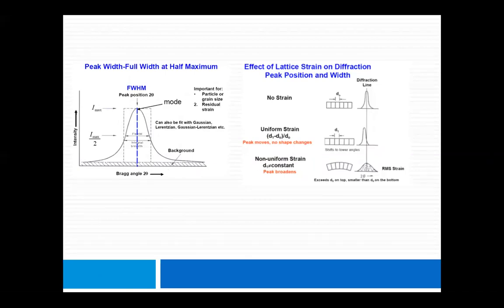So even if you have synthesized particles of the same size by different routes, please remember, same size by different routes, if you measure the size by XRD, you will get different sizes. Why? In case of synthesis by ball milling, stresses are there, so peak broadening will be more because of the effect of stresses. But in case of powder synthesis by chemical route, stresses are almost negligible, so peak broadening will be less.